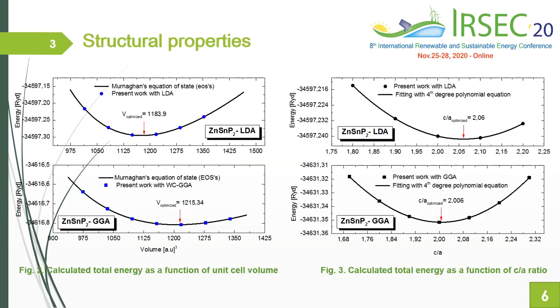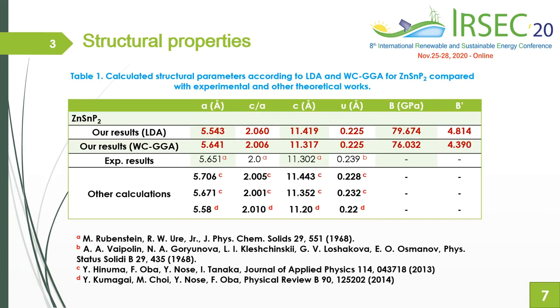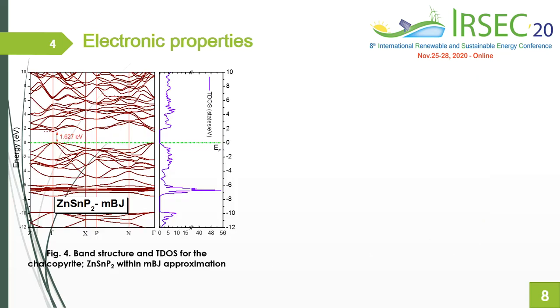In this slide, the relaxed equilibrium structure parameters, such as the calculated lattice constant, the internal parameter u, the bulk modulus B, and its first derivative, were obtained by fitting the total energy versus volume to Murnaghan's equation of state and to a fourth degree polynomial equation, as shown in figures 2 and 3 respectively. This table lists the calculated structural parameters according to LDA and WC-GGA for the ZnSnP2, which are in good agreement with theoretical and experimental results.